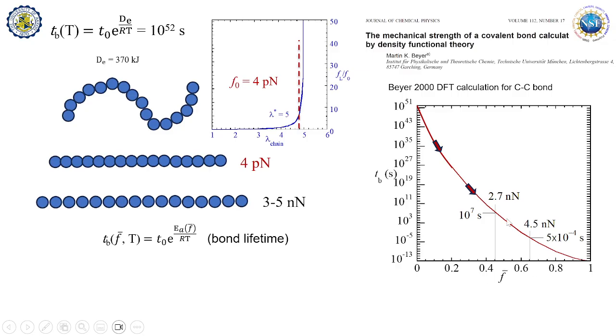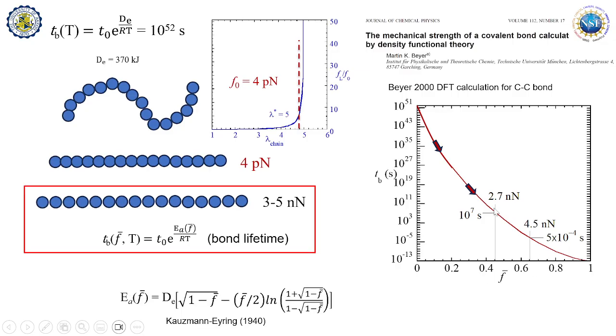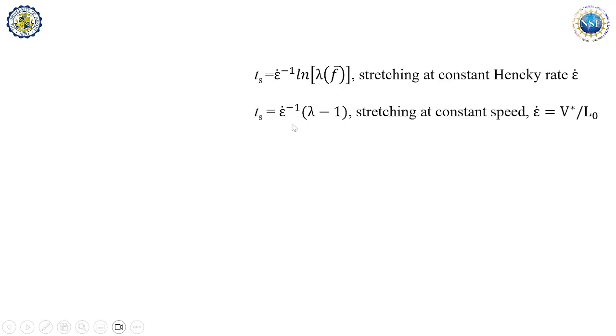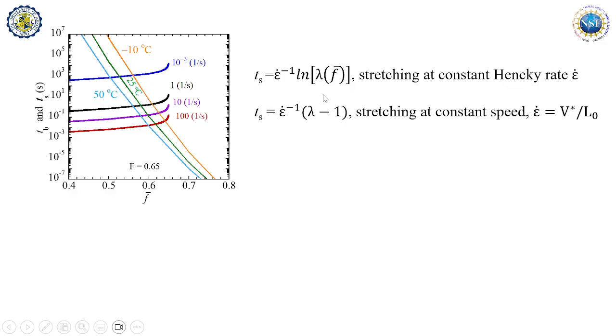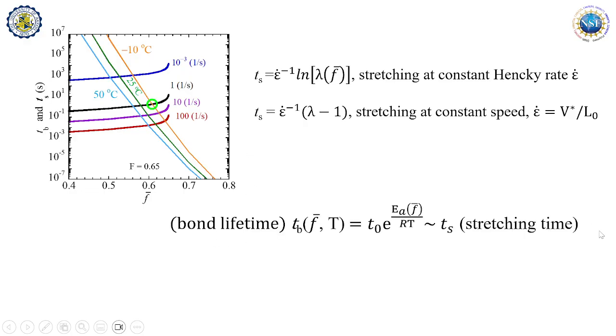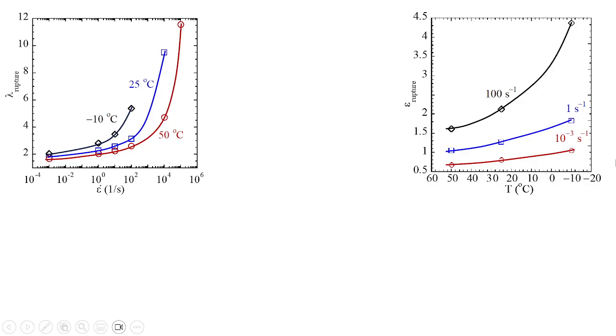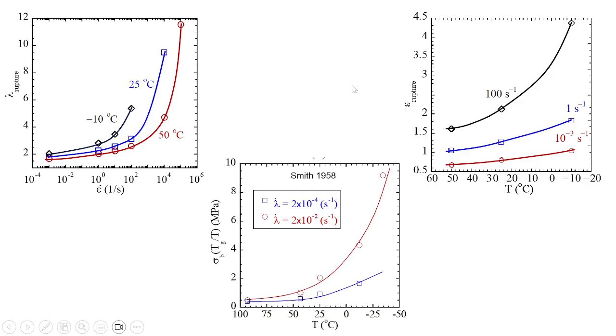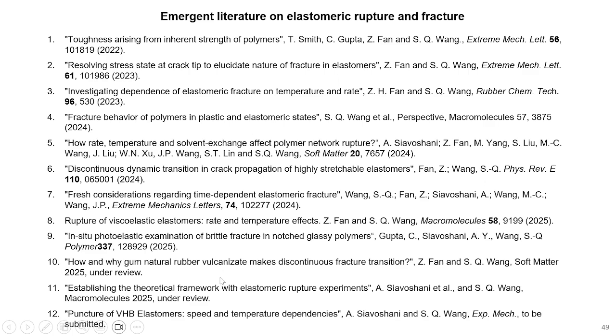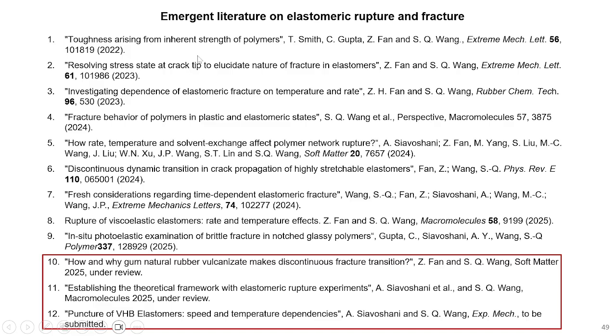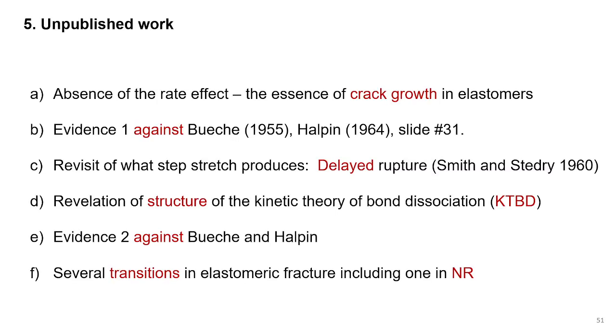So through that insight, I can build a theory about stretching being about the lifetime. Your material lifetime shortens as you stretch more and more, until that time meets the experimental time you have already spent, boom, break would occur. Through that, I could build a theoretical calculation showing how the rate dependence and temperature dependence take place. So these are the papers so far, and we're writing more, and these three are unpublished. If I have a few minutes, I'll show you these unpublished results. None of them has been published.